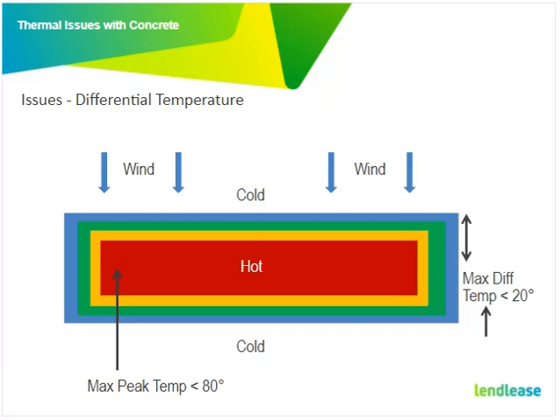The issue of differential temperature is, you've got the inside hot, but then you have issues with the ambient temperature or wind, particularly, which is pretty damaging and basically cools the outside surface. So if you've got 80 degrees in the centre, you get quite a large differential to the outer edge, and that's what causes cracks from differential temperature. Now that is a real, well, I wouldn't say issue, but it's a real effect.